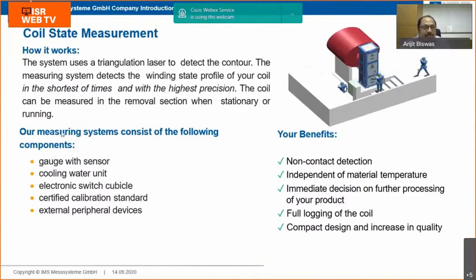As I told you, this gauge comes with the laser, and we also have a cooling water unit to keep things cool for the hot strip mill. We have also certified some calibration standards to check whether the system is working properly or not. The benefits are that we are able to detect the coil's winding quality without any contact. It is independent of material temperature, that is, we can use it on hot as well as cold coils, and we can have full details on logging of the coil in our system, and the customer can decide whether to process it further or not.